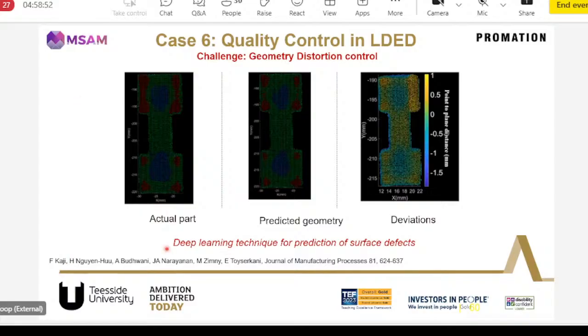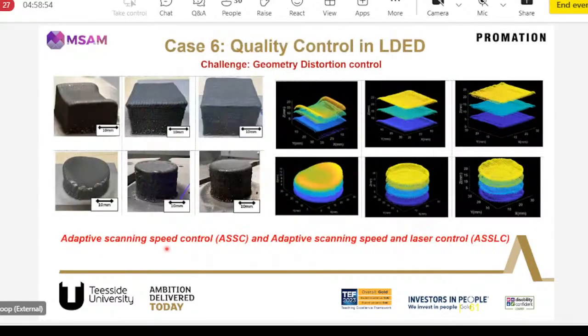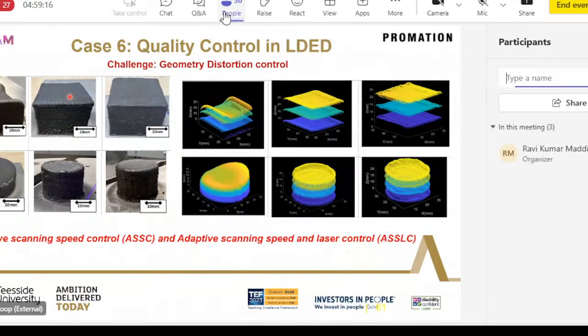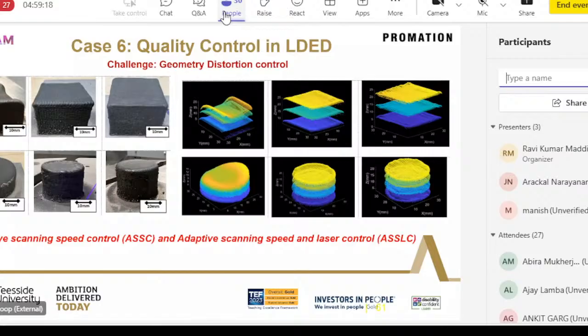Then we used that to control the geometry of the part. So we predicted at which parameters we can generate these sort of defects, what will happen actually, and then we used it to control it. We used two different strategies. One is scanning speed control, the other one is laser and scanning speed control. And then we used them to get a flat surface. So this sort of structure was the initial phase, and then we brought it to the actual flat component. So we could see how the geometry has improved.